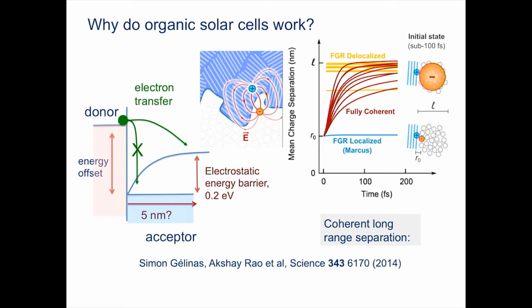So we've used empirical selection, which often doesn't get as much credit for scientific innovation or engineering innovation as it should do, but that's how it is. And what we discovered is that where we were looking at an electron and hole separating between the electron accepting bit, which is the circles here, and the hole accepting bit, which is the blue shaded area above, there was enough electric field between the electron and the hole to warp the color of the blue material a little bit. The electric field generated slightly redshifts the color of this thing, which we could then measure and calibrate and use as a voltmeter.